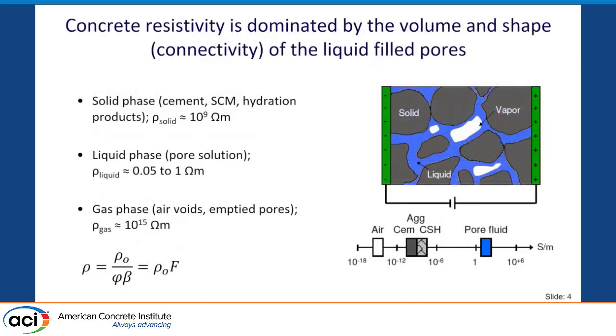What's also important is that conduction in concrete, or electrical current through concrete, is happening through the liquid phase. That's why the pore solution or porosity is really what matters. What you have here is the resistivity of different phases. The solid phase has about 10 to the 9 ohm meter. The gas phase about 10 to the 15, and we all remember that electricity takes the path of least resistance, which is through the liquid phase. You can see it's 9, 10 orders of magnitude lower.